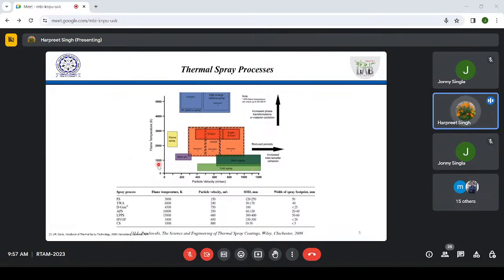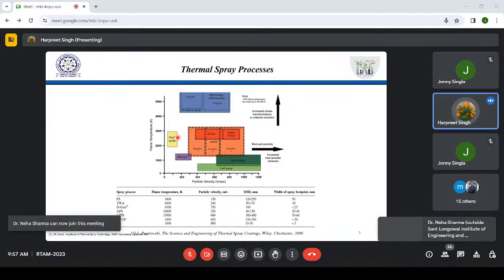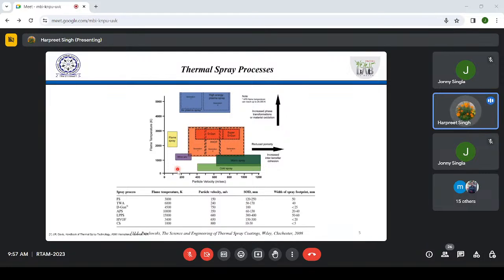The working temperatures are typically less than 1000 degrees Kelvin, right? And you can see HVOF guns, and high energy plasma spray comes here, which has very high temperatures, but the velocities are less. Flame spray lies here, where temperature is significantly higher but the velocity is very low. We do not appreciate high temperature in any process, because it leads to phase transformations or material oxidation, right? The most frequently used feedstock in thermal spray is powder, and powders are very active, so they get degraded when the temperatures are high. That is something we want to avoid.